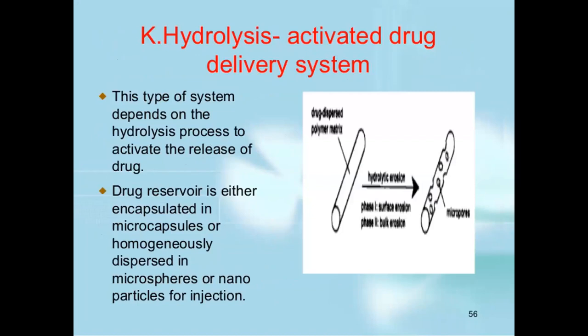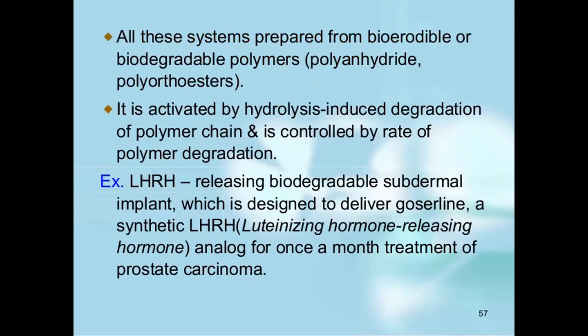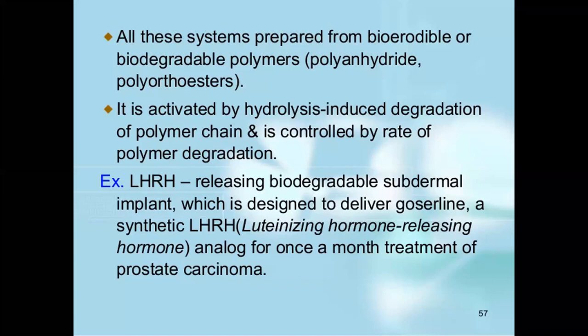Next is the hydrolysis-activated drug delivery system. This type of system depends on the hydrolysis process to activate the release of the drug. The drug reservoir is either encapsulated in a capsule or homogeneously dispersed in a microsphere or nanoparticle for injection. All these systems are prepared from bio-erodible or biodegradable polymers. It is activated by hydrolysis-induced degradation of the polymer chain and is controlled by the rate of polymer degradation. For example, the Zoladex biodegradable subdermal implant — a luteinizing hormone-releasing hormone analog — is designed to deliver goserelin, a synthetic LHRH analog, for one-month treatment of prostate carcinoma.